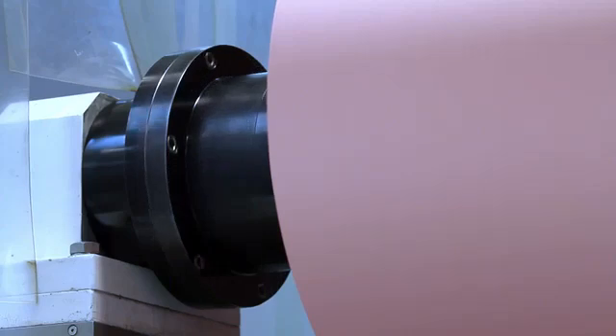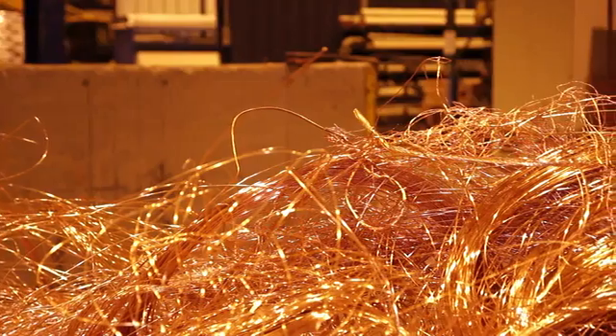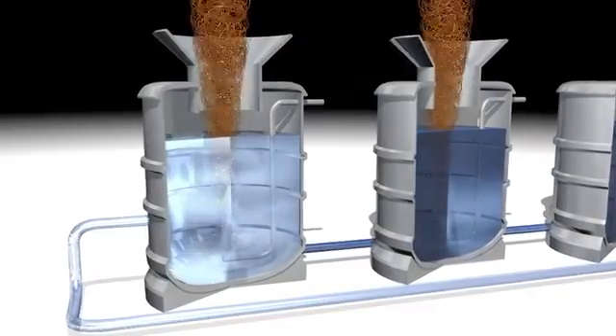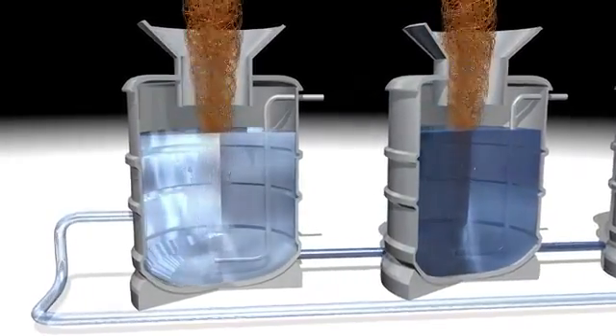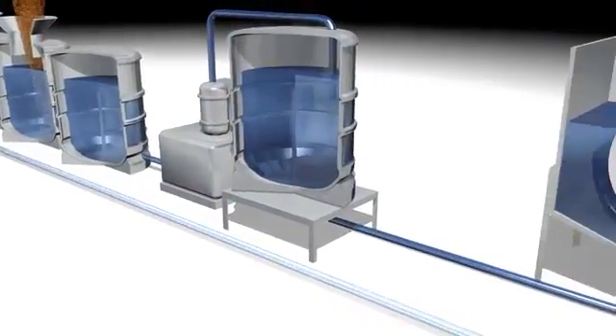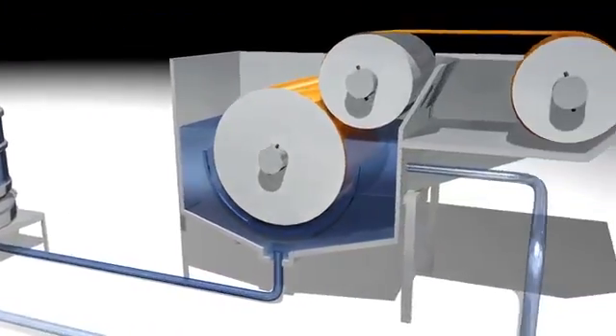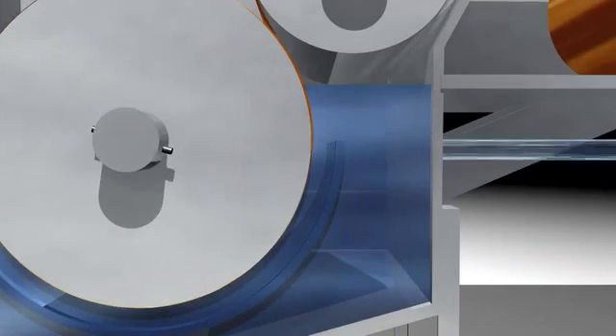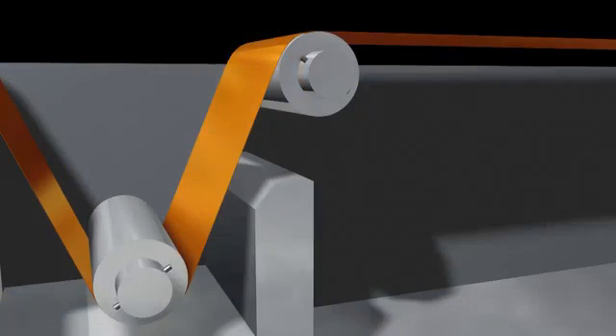First, pure electronic-grade copper wires are dissolved in a sulfuric acid solution, which is then pumped into a closed-loop system passing through filters to the plating drum cells. Current is passed between the rotating cathode and the anodes, electro-forming an endless copper strip.